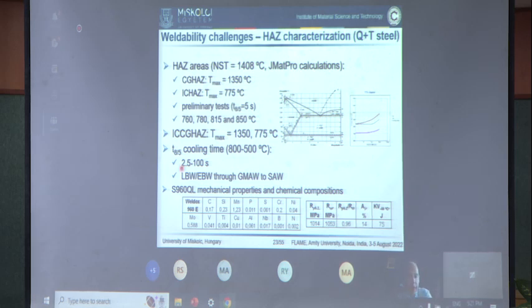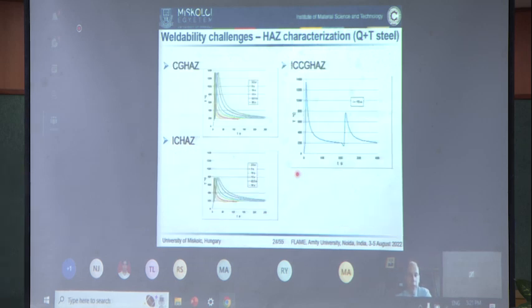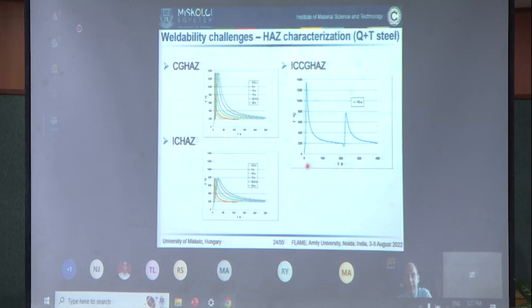So generally 2.5 sec illustrates laser beam welding and electron beam welding circumstances, while 30 sec or 100 sec can be relevant in terms of submerged arc welding or other high heat input technologies. Here you can see the simulated heat cycles for the coarse grain zone, for the intercritical zone, and for the intercritically reheated coarse grain zone. All of these curves were generated based on the Rykalin or Rosenthal 3D model. After the successful simulation, we performed scanning electron microscope analysis.